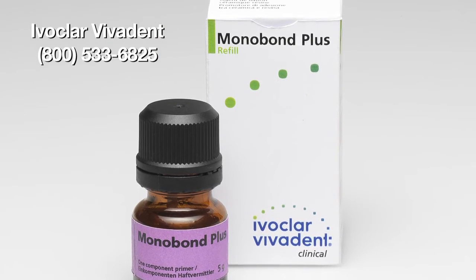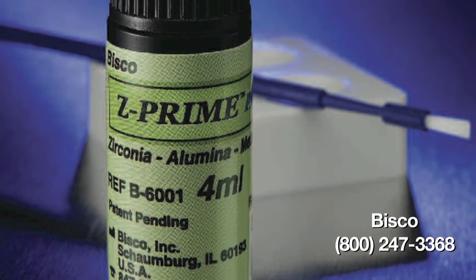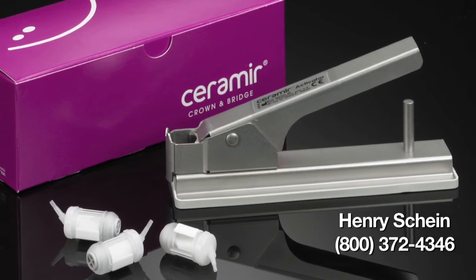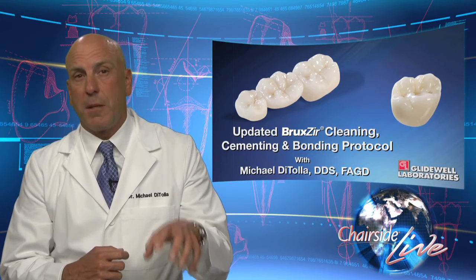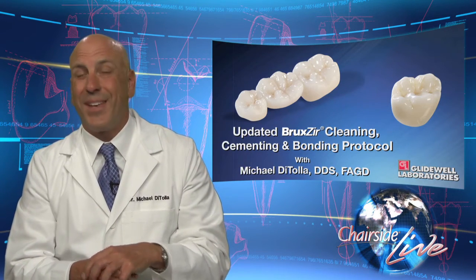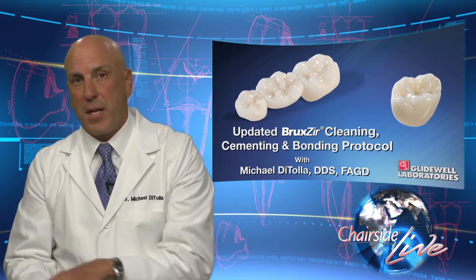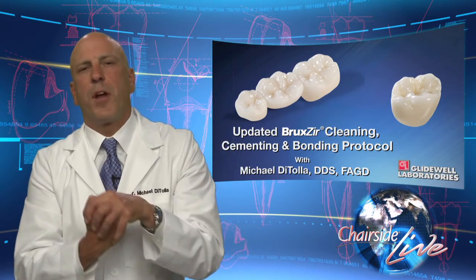What are we going to get to stick to it? You could use something on the inside like Monobond Plus silane from Ivoclar, or Z Prime Plus from Bisco. Both of these products have phosphate groups in them, and that's how they're able to bond to the BruxZir or Lava crown. You could also use a newer cement called Ceramir from a company called Doxa — a cement that actually has phosphates in the cement itself, so you don't need to use a silane; it bonds directly to the BruxZir crown. So anytime a BruxZir or Lava crown is tried in the mouth, it needs to be cleaned with Ivoclean for 20 seconds, then rinsed out. Then you either place a silane such as Monobond Plus or Z Prime Plus, evaporate that, and go through regular cementation steps — or after rinsing the Ivoclean, go directly to the Ceramir cement, which has the phosphate groups in the cement and will bond to the BruxZir crown.